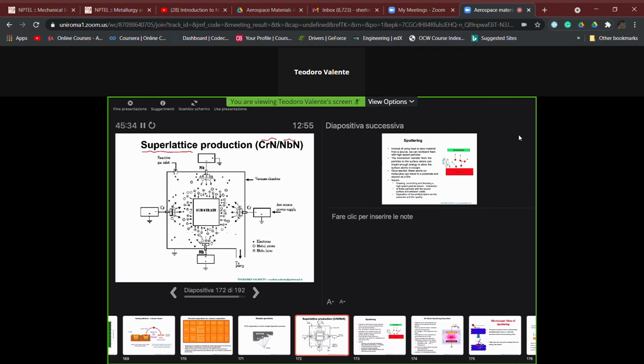It is a sputtering system, so we do have, as we will see later, ions which are able to sputter out materials from our source, our target. There are some special cases in which we can use a vacuum chamber filled, as we see here, by a reactive gas inlet. For example, in this case, we can start by using nitrogen as a reactive gas inlet. We can have a source of chromium, we can have a source of niobium, and niobium and chromium atoms react with nitrogen to form a chromium nitride and niobium nitride.